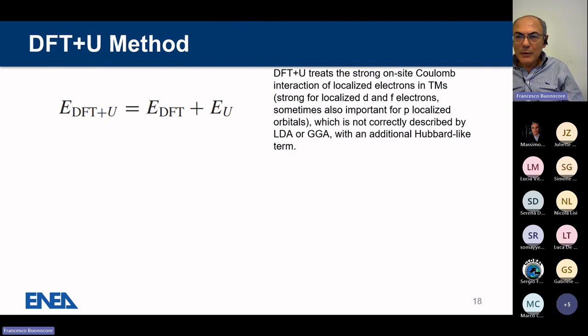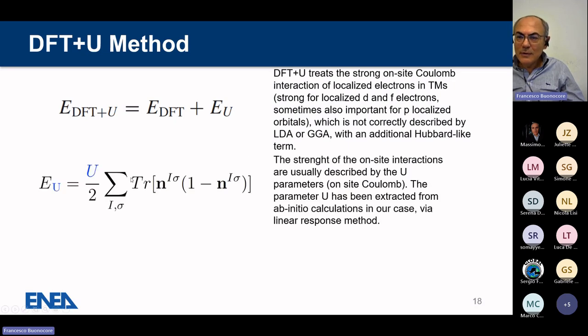Something more about the Hubbard approach. Really, transition metals have strongly interacting d and f electrons, that occupy the d and f shells of the electronic structure of the atoms. They are strongly interacting, and they have a strong correlation that density functional theory alone is not able to describe. So we need to go beyond DFT by introducing these corrections, where this correction takes into account the strength of the on-site interactions. This is done by introducing U parameters, that can be calculated by ab initio approaches via linear response method or by experiments. But anyway, we prefer the first approach.